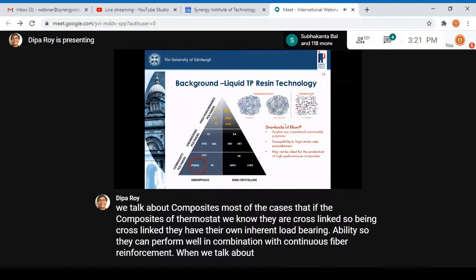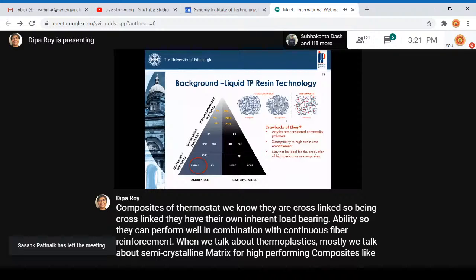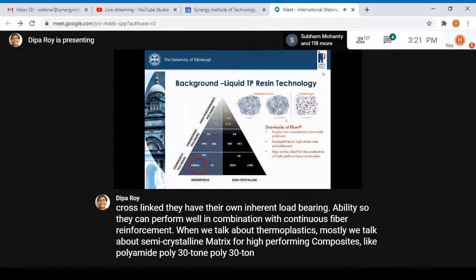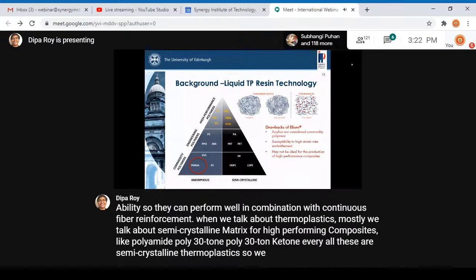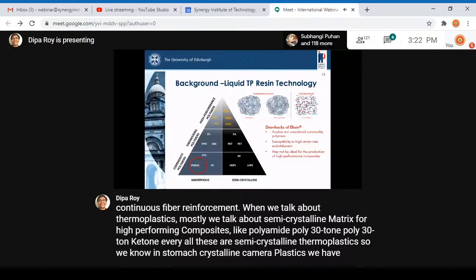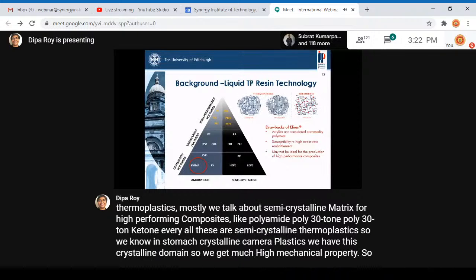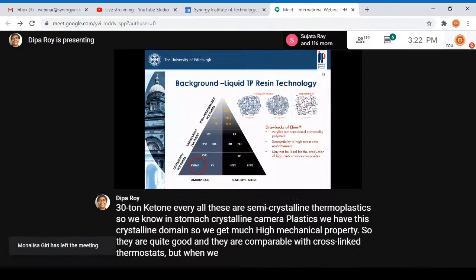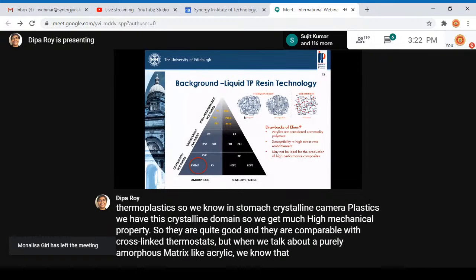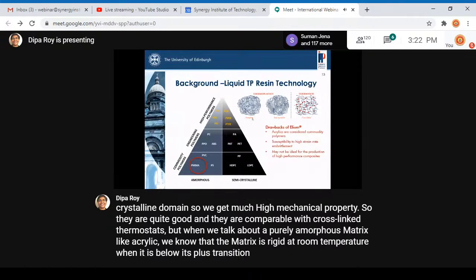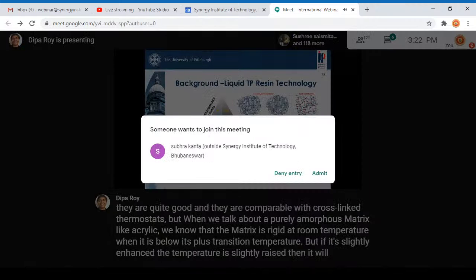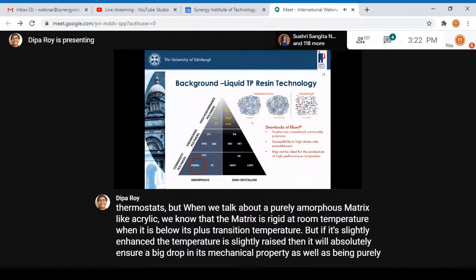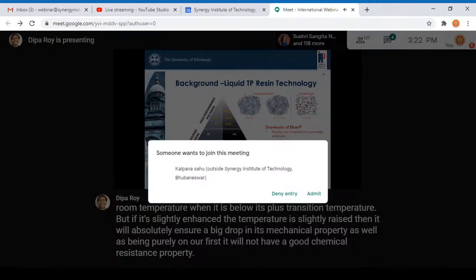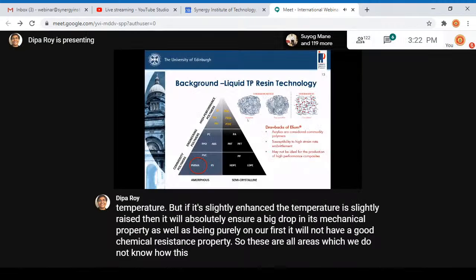When we talk about thermoplastics, mostly we talk about semi-crystalline matrices for high-performing composites, like polyamide and polyether ketone. All these are semi-crystalline thermoplastics. In semi-crystalline thermoplastics we have crystalline domains, so we get much higher mechanical properties, and they are compatible with cross-linked thermosets. But for a purely amorphous matrix like acrylic, the matrix is rigid at room temperature when it is below its glass transition temperature. If the temperature is slightly raised, it shows a big drop in mechanical property. Being purely amorphous, it will also not have good chemical resistance. So these are all areas where we do not know how these composites are going to behave in future.